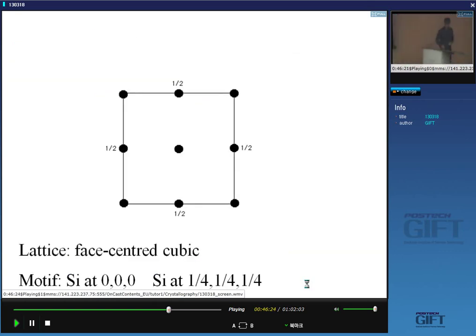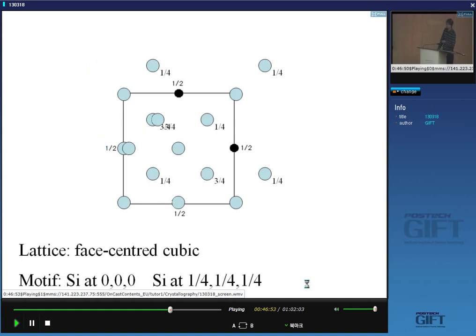So let's imagine that we have our cubic F unit cell, and the structure of silicon is exactly like the structure of carbon diamond, that you have a silicon atom at 0, 0, 0 and a silicon atom at a quarter, quarter, quarter, and we construct that by placing that motif on every single lattice point. So here is the first motif and so on. So this is the structure of silicon. And we can start to ask questions now. How will this differ from, say, the structure of copper in terms of X-ray intensities or electron beam intensities?